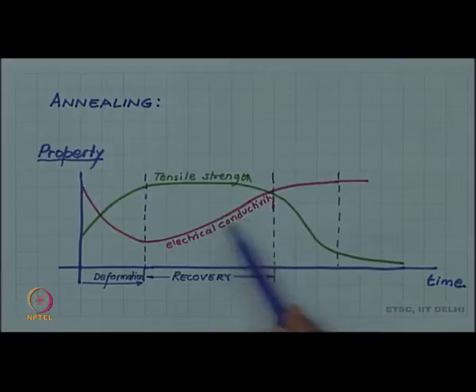Electrical conductivity changes rapidly and restores more or less to its original value prior to deformation. Electrical conductivity shows significant change during recovery, whereas tensile strength does not show much change. Also, there is not much change in the microstructure.